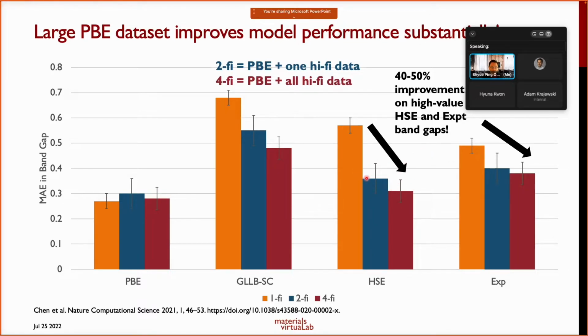So now actually our HSE and experimental band gap errors are almost in line with our PBE prediction error, right? Now, whenever I show this result, people are very skeptical. They think, wow, this is sorcery, right? Because you don't actually have more HSE data, you don't have more experimental data, but somehow the performance on your HSE and experimental data suddenly improved by 40 to 50%. You're getting something for nothing, right? And there's actually a good reason for this.